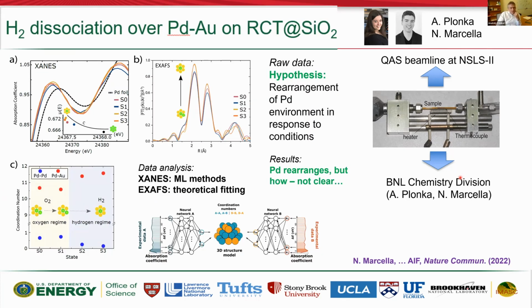The second set of data, the same samples, the same reactor, was brought to the beamline. We collected that at NSLS-II under in situ conditions. We obtained data both in XANES and XAFS. And you see that there are clear changes, and XAFS is a more traditional technique. So we can start with that and show you that in the process of progressive hydrogenation, or exposure of the sample to hydrogen before the reaction, the peaks corresponding to the first nearest neighbors, in this case primarily palladium-gold because palladium was very dilute, increased. And that would be consistent with palladium having more neighbors. That's sort of intuitive.